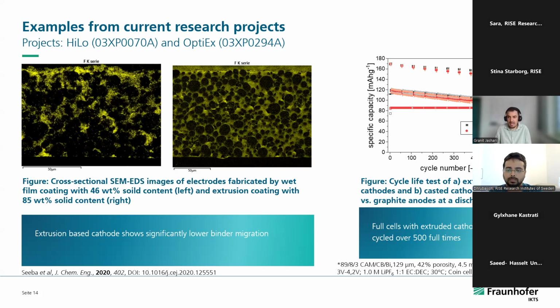You can see how well the binder is distributed in the extrusion process, since there is a really low solvent amount, and that's why during the drying there is no binder migration compared to the wet coating process. As well, on the right side, you can see the extrusion and the tape casting over 500 cycles. This was to confirm that the extruded electrodes can also run for a really long cycling life.